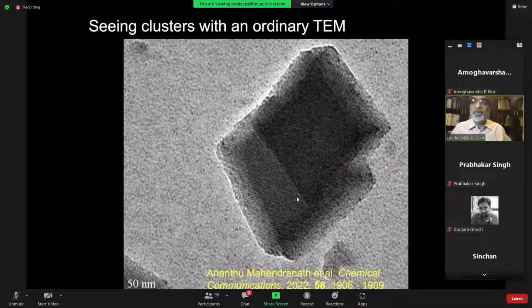Now, I said synthesis is there. So therefore you can get crystals, and these are beautiful crystals. What is shown here is silver 29. One thing that we have been struggling with for quite some time was to image these crystals, large crystals that you crystallize, under an electron microscope. This is because a high energy electron beam damages this and causes aggregation. But recently we have been in a position to see these crystal lattices with a regular, ordinary transmission electron microscope available anywhere. There are signs of aggregation, as you can see, but you see these crystal lattices very clearly. Now, you see an atomically precise cluster crystal lattice.